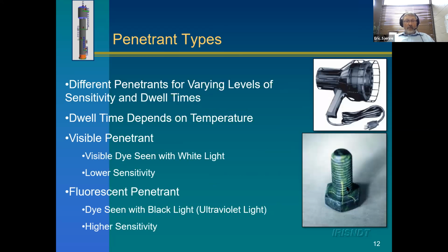So with this, it's really the same as MPI. There's a visible penetrant, so that's just visible where you use it on a surface and you see the cracking, and then there's a fluorescent penetrant, and that's the same kind of deal as MPI where you need an ultraviolet light to show where the defects are on the surface. They're both visual, so it's just done visually. You just look and see where the penetrant is. And like with MPI, the fluorescent penetrant is more sensitive. It takes longer to use, but it's more sensitive.